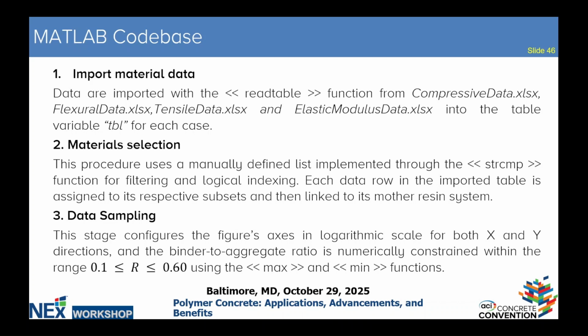I also did the material selection by separating the mother resins from the subset data. And I clamped the data from 0.1 to 0.6 because we need a composite material. Anything beyond 0.6 is going to be a highly resin-dominated material. But we are more interested in the composite material, to see how we get the balance between the polymer and the aggregate.